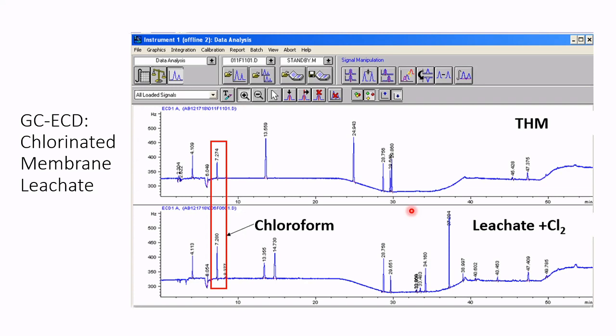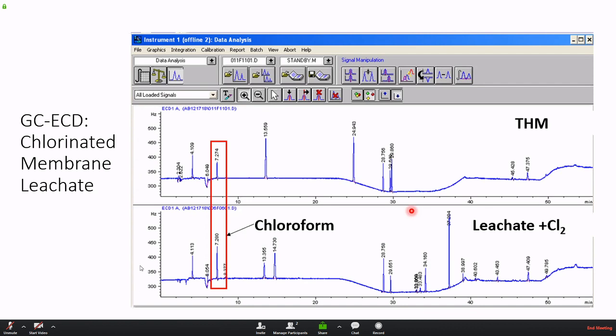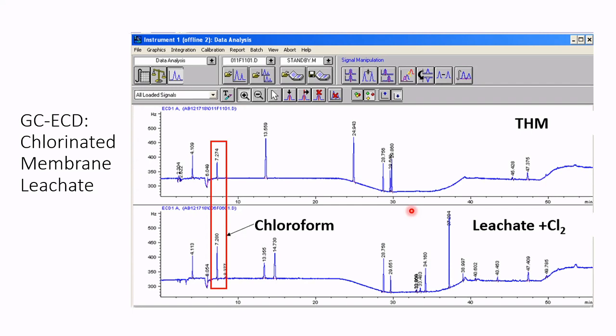So what we did here was I put membranes into the sample bottle, let that leach for X amount of days, I think it was 5 days, take the membrane out and chlorinate whatever has come off of that membrane. And what we found was that, in fact, there are several byproducts that come from the chlorination of what is coming off of these membranes. So you see that one of the peaks is around 7.2 minutes, and we ran up top a sample, same method, of THMs, trihalomethanes.